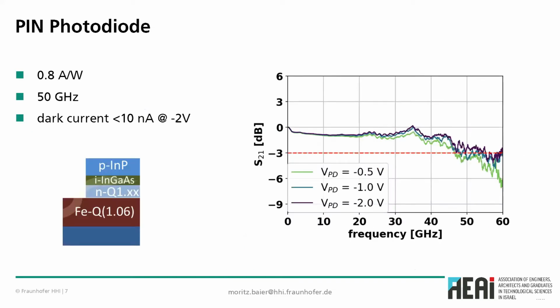Another highlight of our technology is a very fast photodetector that is integrated in the technology. It has up to 50 gigahertz of bandwidth, around 0.8 amps per watt of responsivity, and a pretty low dark current below 10 nanoamps, typically around 2 nanoamps at the normal bias operating conditions.